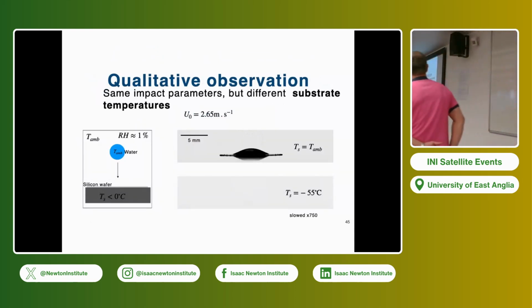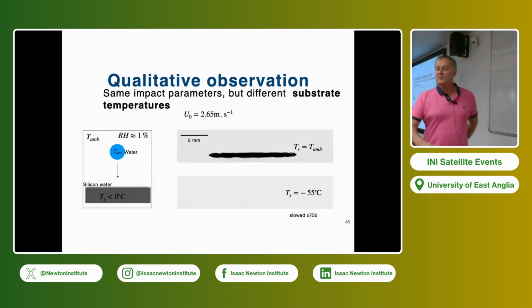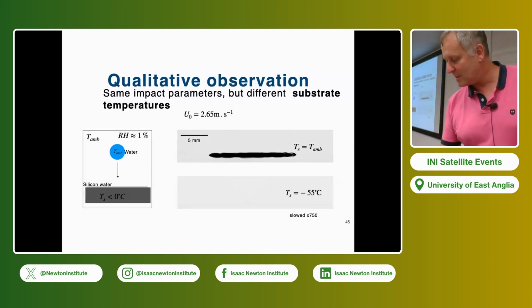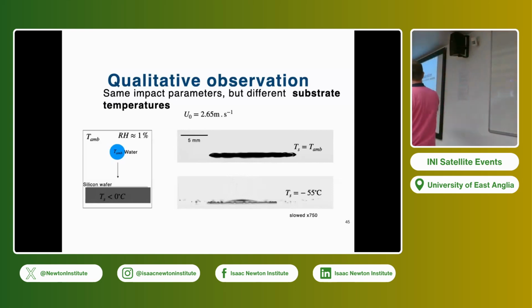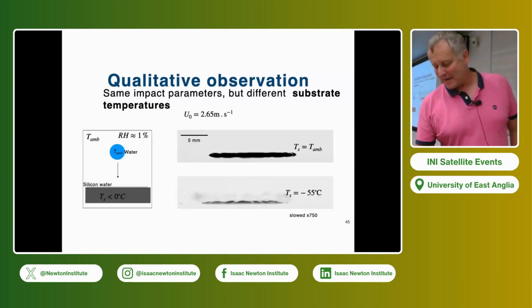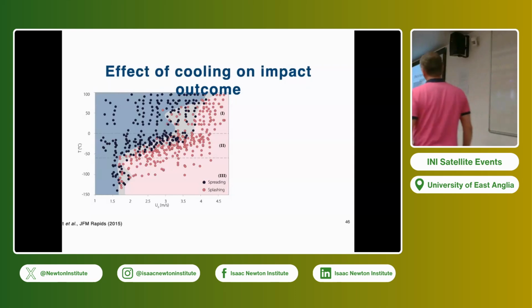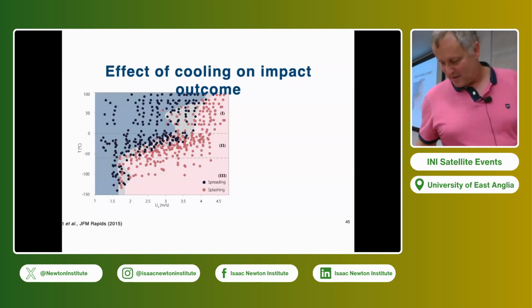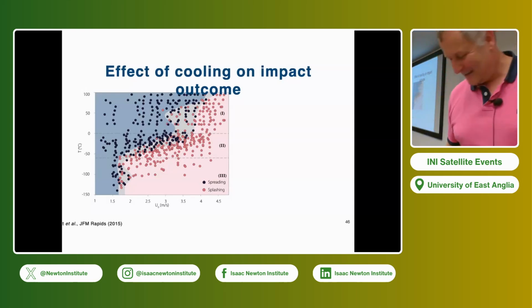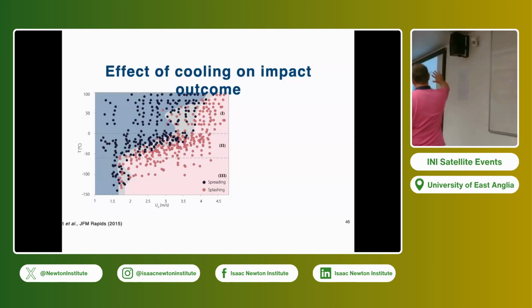The same drop impacting on a room temperature substrate is definitely spreading, and at the same velocity, with everything the same except the substrate at minus 55 degrees, you have a nice splashing. So definitely, a cold substrate makes splashing easier. And if you look at this curve, we can show as a function of the velocity and of the temperature of the substrate that there is an evolution of the velocity as a function of the temperature. And we actually use the theory of Riboux and Gordillo to treat this data, particularly in this regime.